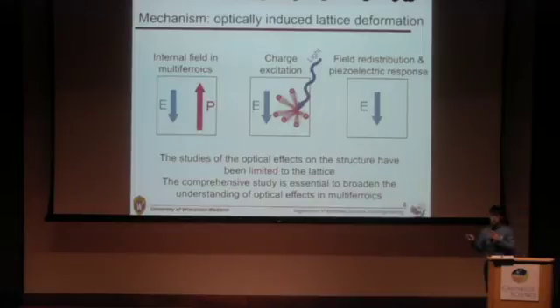So ferroelectric and multiferroic systems have the polarization and internal field which have opposite directions to each other. And when the light source excites the charge carrier, the charge carrier can redistribute the internal electric field. And as a result, the converse piezoelectricity or piezoelectric response initiates. And this is the source of the lattice distortion, the deformation by optical excitations.